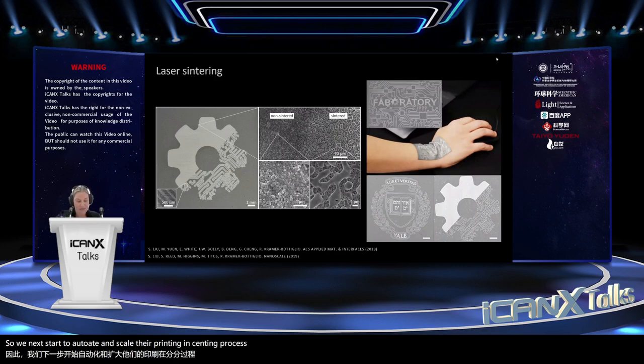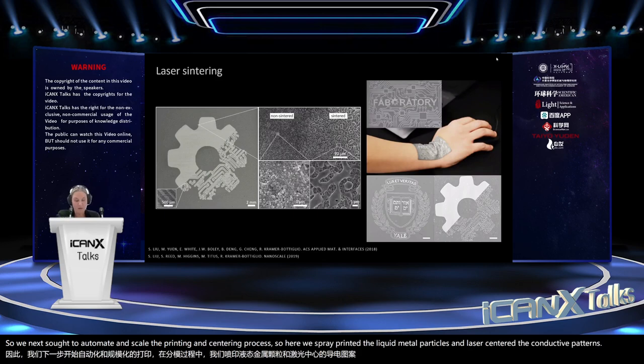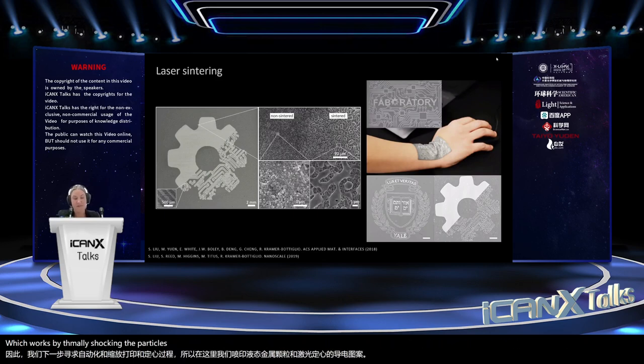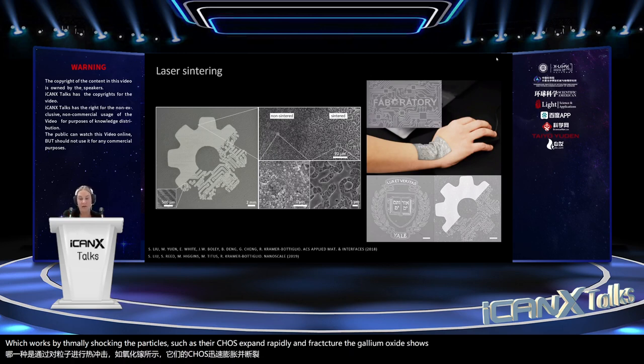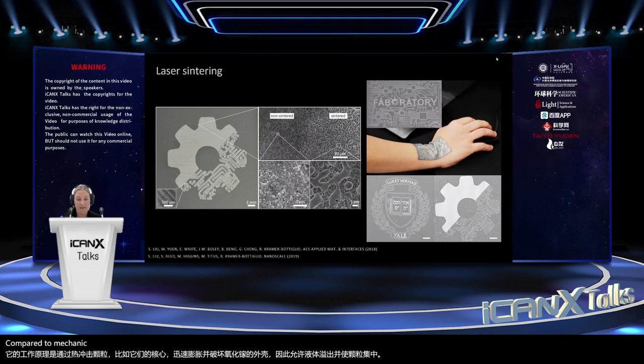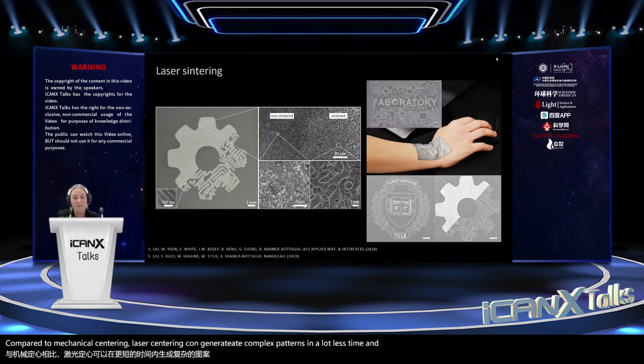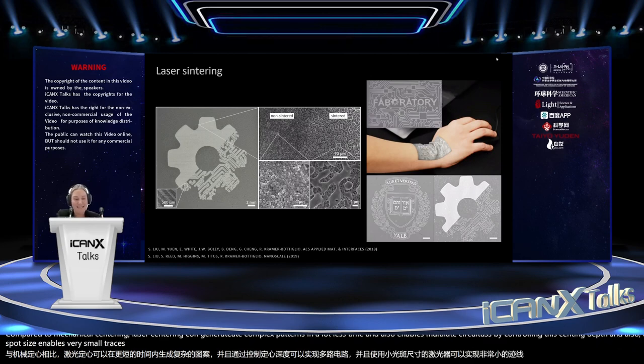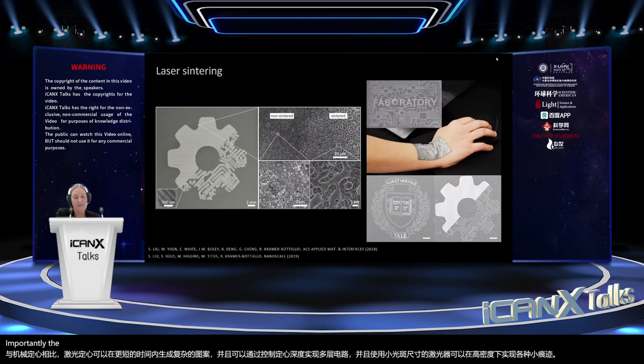So here we spray printed the liquid metal particles and laser sintered the conductive patterns, which works by thermally shocking the particles, such that their cores expand rapidly and fracture the gallium oxide shells, therefore allowing the liquid cores to spill out and sinter the particles. Compared to mechanical sintering, laser sintering can generate complex patterns in a lot less time and also enables multi-layer circuits by controlling the sintering depth. And also using a laser with a small spot size enables very small traces at high densities. Importantly, this sensor fabrication process increased our device yield to over 90%.